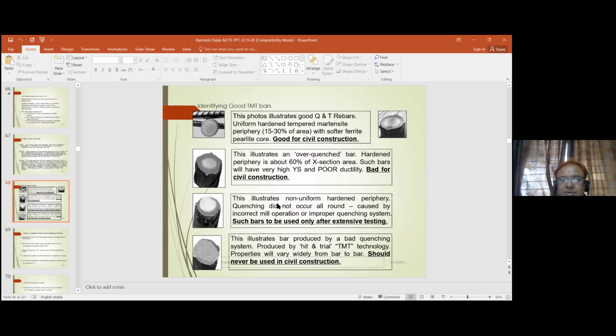This is over-quenched. This illustrates a non-uniform hardened periphery; quenching did not occur all around. Some manufacturers are not going for quenching. What we see in the video, they just dip the bar in the water tank and remove it. So a perfect TMT bar will not be manufactured in that company. These will be harmful for our site. This is the exact 15 to 30% martensite area, and the others are the soft core. So how to know?